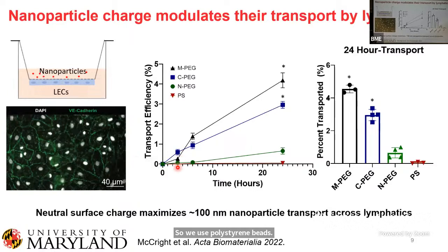And what you can appreciate is that adding charge really has differential effects on the transport of those particles. So if you're looking at these N-PEGs, so those are the amine-terminated PEG-coated particles, these are not transported very effectively, but when you have a negative charge, and even more so when you have a neutral charge, you get quite a bit of transport across lymphatic endothelial cells.